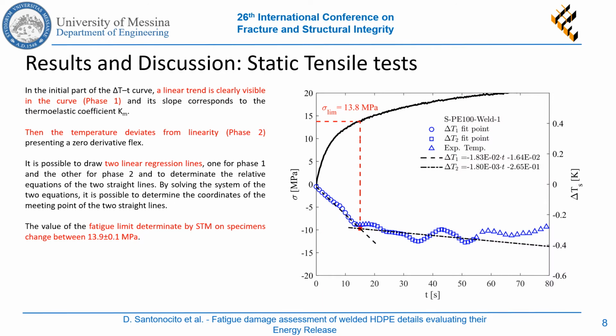During static tensile tests, the evolution of the specimen's surface temperature has been evaluated by means of an infrared camera. The applied stress is reported versus the specimen's surface temperature variation, estimated as the difference between the instantaneous temperature and the initial temperature of the surface recorded at time 0. The temperature data has been filtered with the Loess filter with a data span of 10% in order to reduce the outliers and highlight the thermoelastic trend.